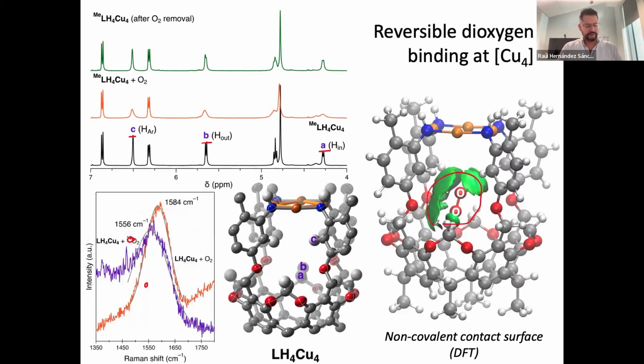And most importantly, we can corroborate this with Raman spectra, where the O2 unlabeled, or O16, shows up at about 1584, and when we enrich it to 18, we see a shift towards 1556. Not quite the shift that you would expect, however, it is a shift in the direction that you would predict.